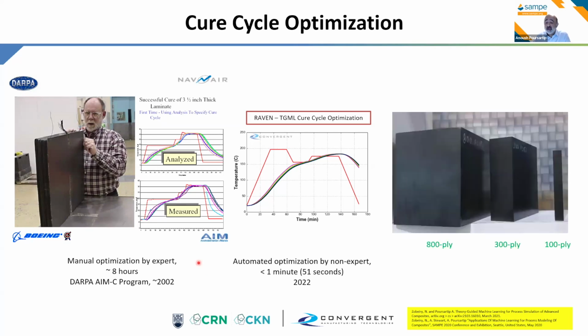What I'm showing you here is some panels that were made by a user of simulation, where they've made 800 ply thick, about 6-inch thick, about double the thickness here. And you can see the quality is absolutely excellent, and they were able to get totally acceptable cure cycles.